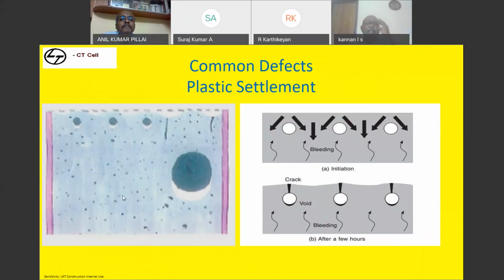Plastic settlement. You can see concrete bleeds, the bleed water comes out. When the bleed water comes out, the concrete wants to settle. Since reinforcement bars are rigid members which do not allow the concrete to settle, still the concrete settles, which leaves a line on the top of the bar. That means you are able to see the layer lines at which the reinforcement is laid. The only problem with this is it creates a void at the bottom of the reinforcement, because since it is settling, the bond strength is lost to some extent.